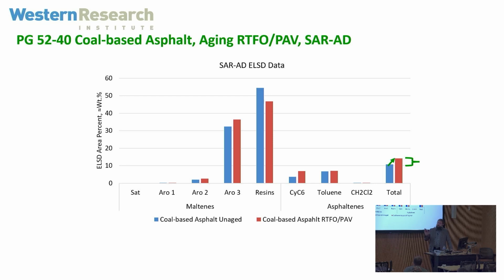So this data here is looking at the different chemical classes of chemicals that are in our product. And so I'm not going to go through all of these. The main thing is that you see that there's some over here that we call maltenes, and then there's some that are called asphaltenes. Asphaltenes are kind of like the particles suspended in solution. And it's very normal in an asphalt that you take some of the liquid phase, as it oxidizes, it becomes part of the particle phase. So that's a normal thing that happens. And so this total is the sum of these three things here. This is basically the total of the particle phase.